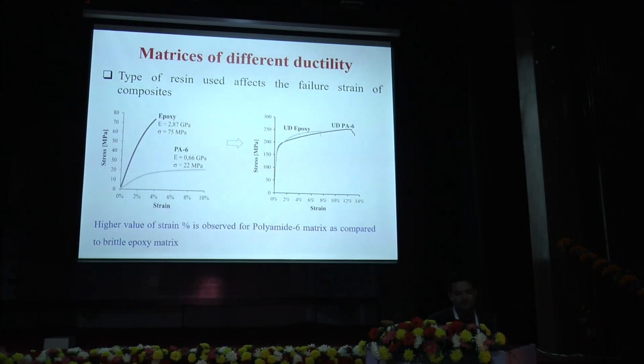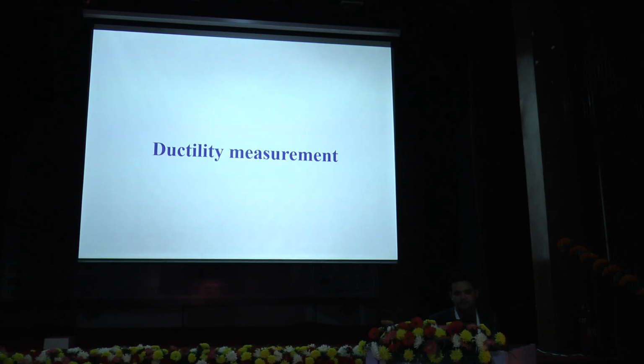You can see this is a comparison between epoxy and polyamide, and a higher value of strain percentage is observed in polyamide matrix as compared to the epoxy matrix, which is the brittle one.